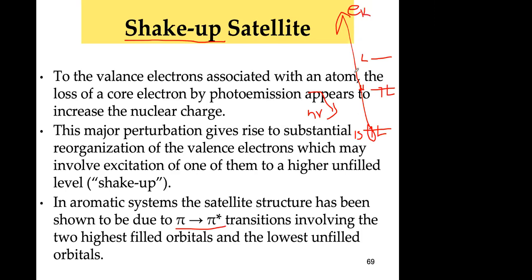But what happens? It could happen that some part of that kinetic energy can be used to move this electron to a higher level. It could be from π to π*. So this electron has a lower energy than the electrons that don't produce shake-up. So I'm going to put here a star, because that electron has given part of its energy to have this transition, π to π*. And that's called shake-up satellite peaks.